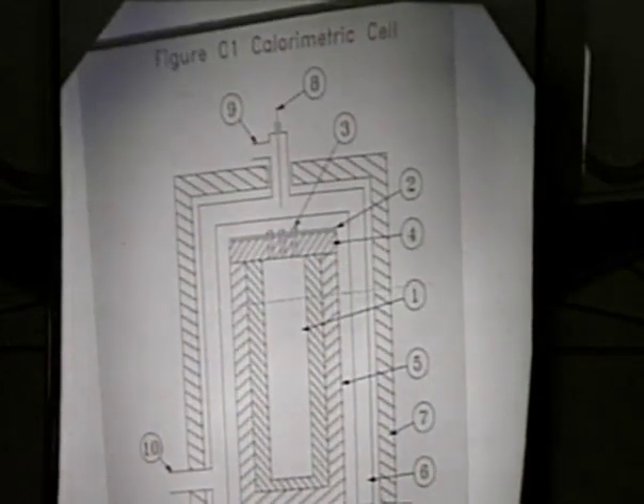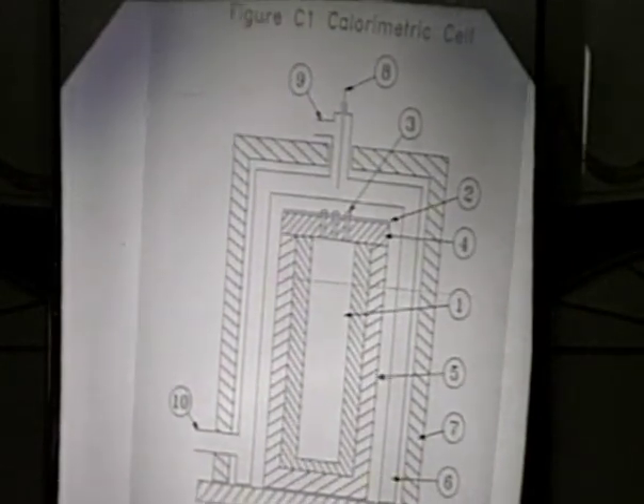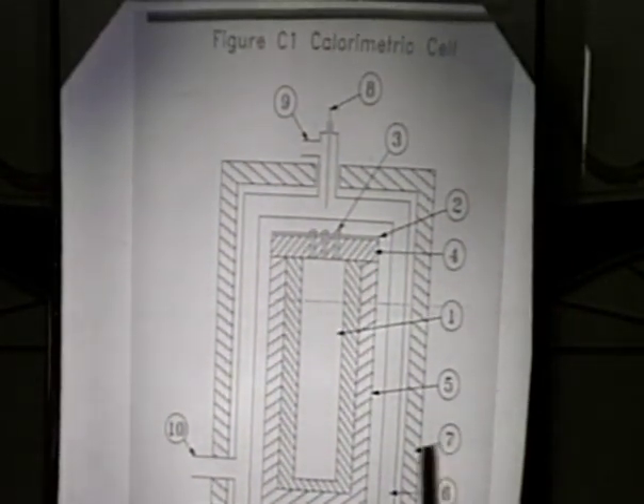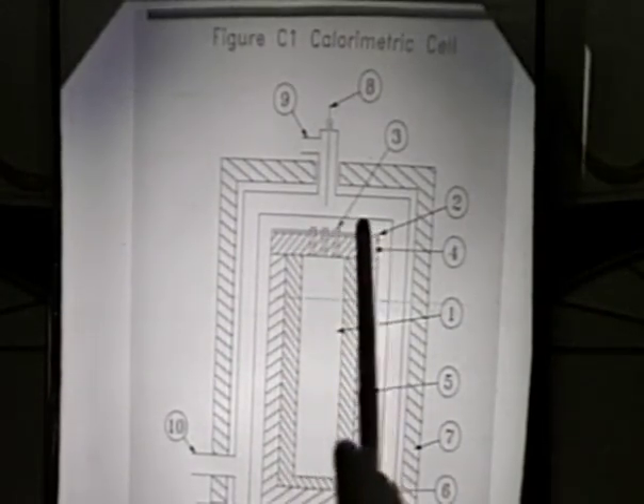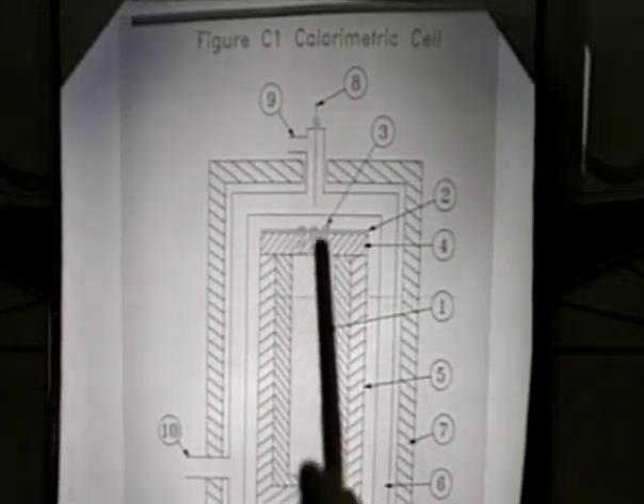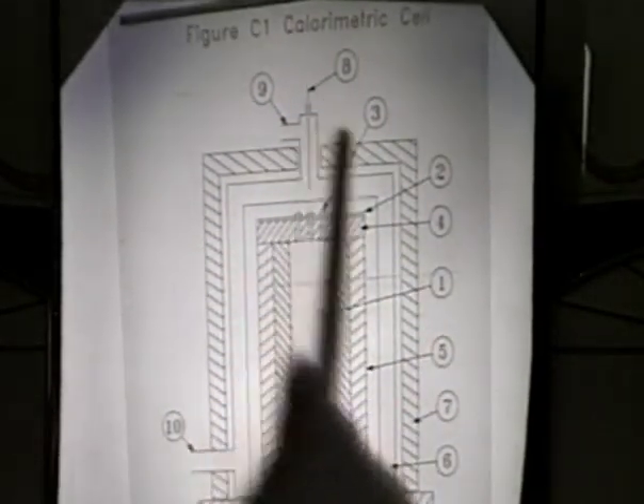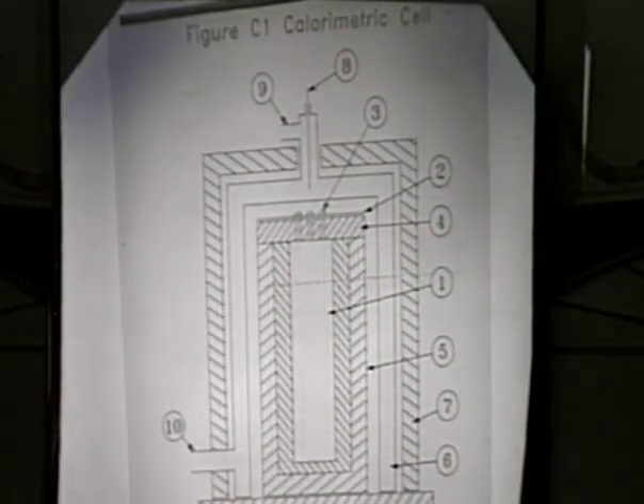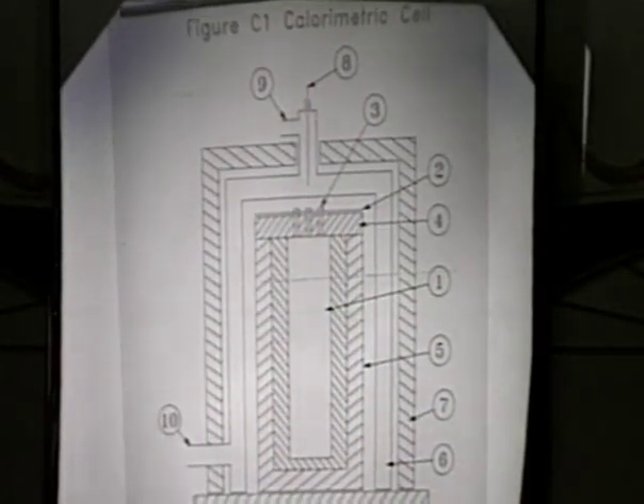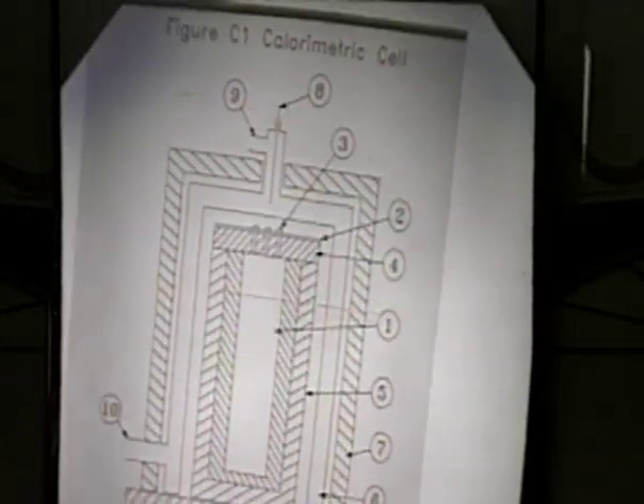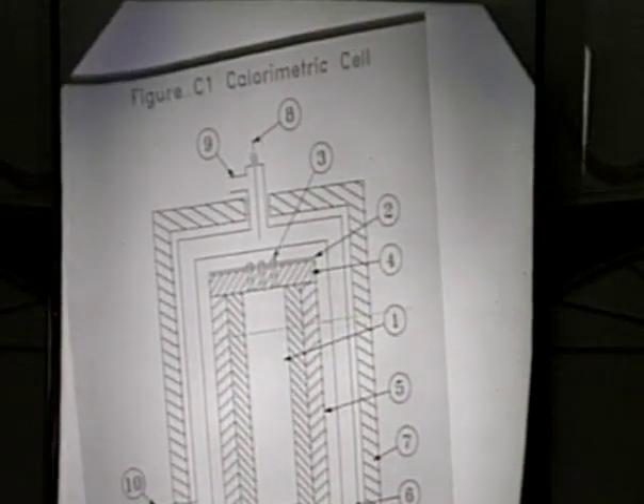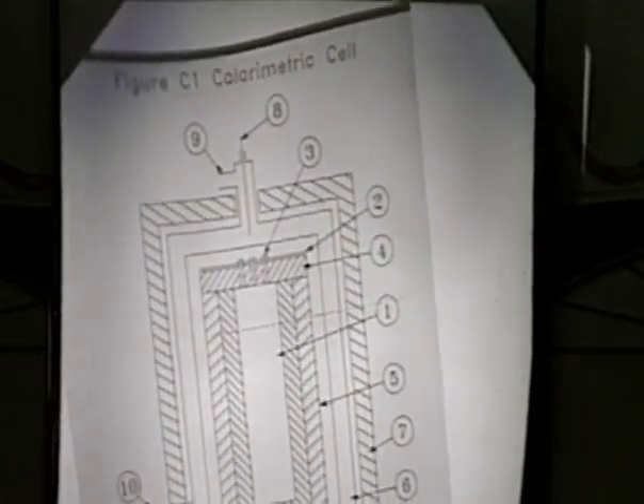Then we redesigned the experiment pretty much, and the calorimeter was designed rather specifically for this experiment rather than being the old calorimeter. But the principle is pretty much the same. We have the inside aluminum chamber in which the cell resided, and then some brass pieces coming out here which connected to the plate, which was the principal heat flow region over there. There's a water jacket flowing around here, plenty of thermistors checking the temperature, and insulation around the system. We believe the calorimeter is accurate to a fraction of a milliwatt. In other words, we can measure changes in power with pretty good accuracy. It's all hooked to computers and recorded automatically.